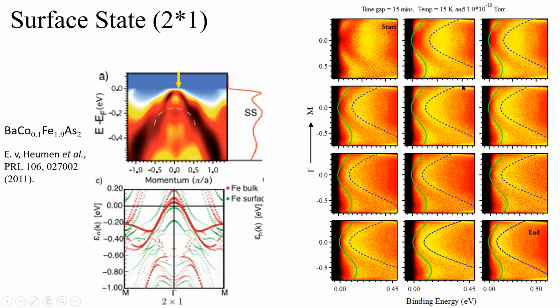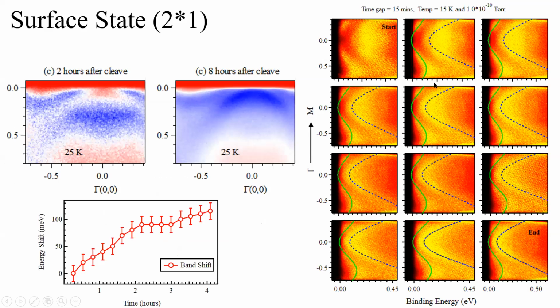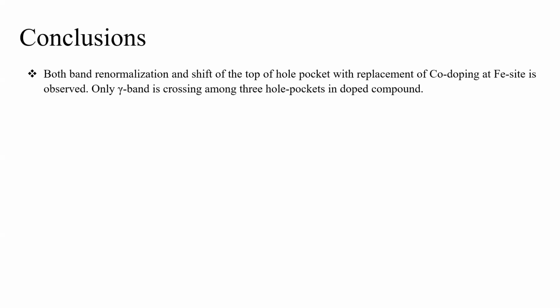So even if we have 10^-11 torr pressure in our chamber, we do see a significant change in the surface state of the compound. Now, there are already studies on similar compounds, BaFe2As2, and there they have found a similar type of surface state crossing at this energy. So we are expecting that the surface state that I've drawn here is because of the 2x1 type of surface reconstruction, and because of that we are getting this type of dispersion. So with this, I will conclude my talk.